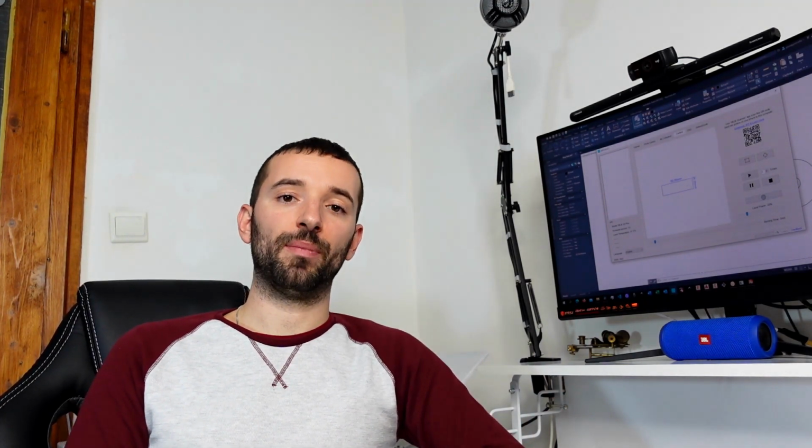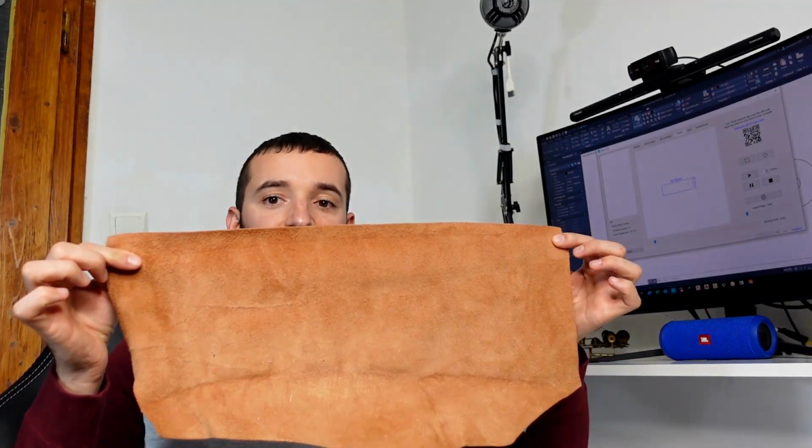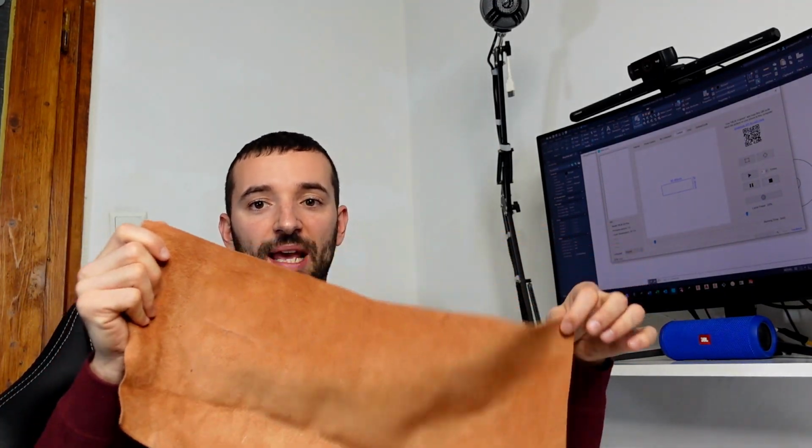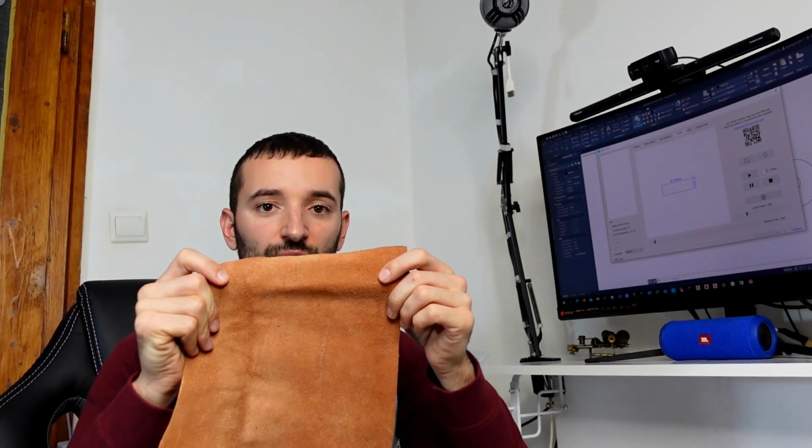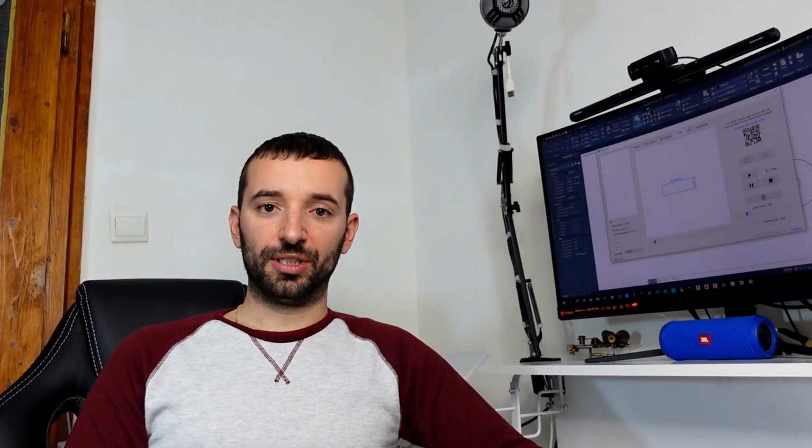So it was clear at that point that the only way to go all the way through the sheet of leather with the laser is to compress the fluffy layer, the corium. At least to do that temporarily while you are cutting. The same way it worked out with the sacrificial sheet and weights on top. And that's when I started experimenting with an iron. So I started to iron the sheet in the area where I wanted to perform the cut, and that turned out giving some good results.